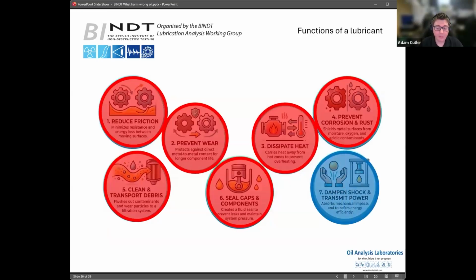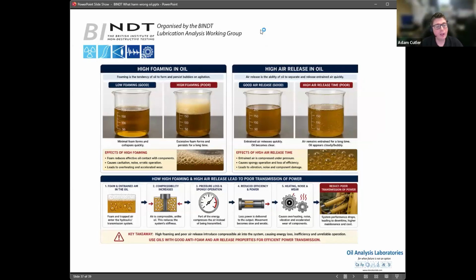We also want to, as well, dampen shock and transmit power. So if any of you have ever put your foot on the brakes and it's not gone too well, this can be down to air in the brakes. And so obviously that's a safety issue, but this also happens in anything in hydraulic power. So air obviously is compressible. And so foam in a lubricant or high air release tendency to a lubricant can all lead to uncontrolled movements, can lead to safety issues because it's uncontrolled, but can also over time, because air is compressible, that air gets superheated. And so over time, that heated air will burn the oil around it and form little soot particles. And so you can actually get a process called microdieseling. So the oil actually over time starts to soot.